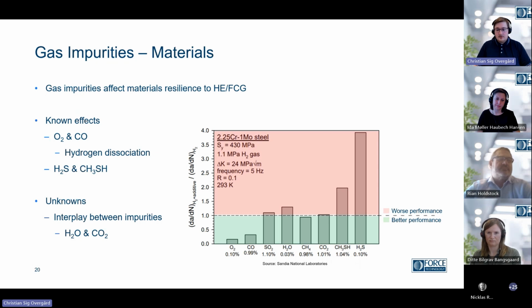Oxygen has a large impact in reducing the susceptibility of the steel tested to fatigue crack growth. The exact reason is a bit more complicated, but in short, as far as theory goes, it prevents dissociation, and as such prevents the hydrogen from entering your material. Other known effects are the more damaging effects of hydrogen sulfide and methane thiol. These, as you can see on the furthest right of the figure, even in small quantities, for instance hydrogen sulfide, are quite damaging when compared to a pure hydrogen atmosphere.